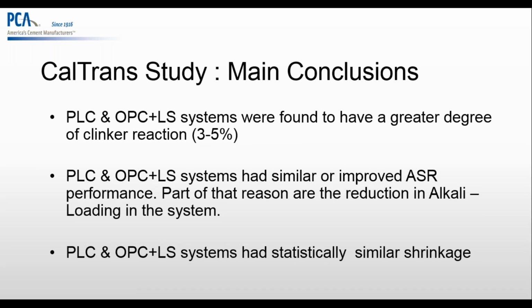There was a study by the California Department of Transportation recently, and these are the main conclusions. I'm not going to go through all the study, but what they've seen is that the PLC and the OPC plus limestone systems, right? They took OPCs and they added limestone, and they were found to have a greater degree of clinker reaction. In the testing that we've done and that I've seen in the past, it's pretty much equal, but it all depends on the degree of the reactivity of the clinker and the grinding as well. So in their conclusions, they've seen an increase of clinker reaction, which is very good also. The system also had similar or improved ASR.